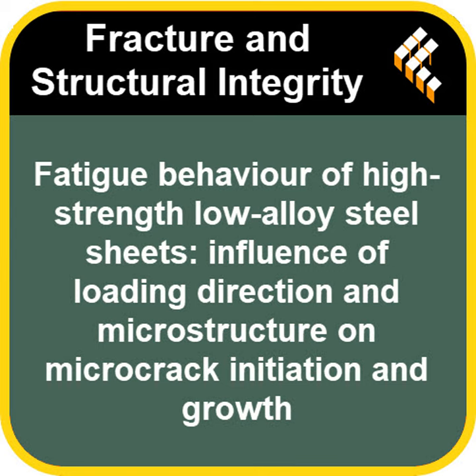Pretty much. But as you increase the strain, plastic deformation spreads out more. And then crack propagation, how fast those initiated cracks grow, becomes the main factor controlling the fatigue life. And this propagation seems strongly linked to the formation of those subgrains we talked about. So let's picture the cracks themselves. At low strain, what did they look like in RD versus TD?